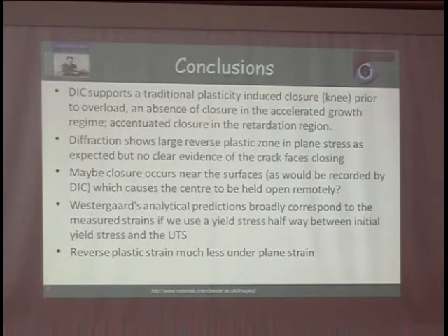And then finally, the reverse plastic strain under plane strain testing is much smaller, a lot smaller than the plastic strain under plane stress, which again is not perhaps surprising. And indeed, after overload, you really don't see a traditional reverse plastic strain area. It is too small for me to measure with a 0.5 millimetre gauge volume.